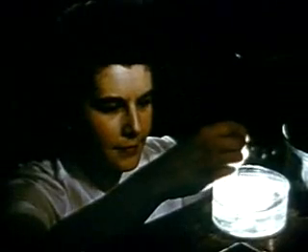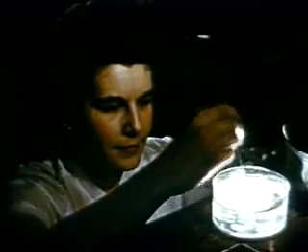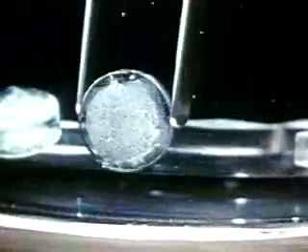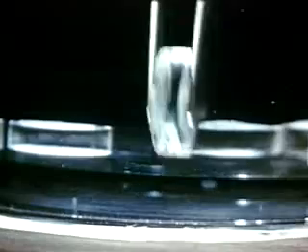okay. The liquid in the bowls is called xylol. It's something like benzene. It has most nearly the same index of refraction as glass, and because of this, tiny defects in the blanks show up better. This is just one of many 100% inspections that take place during the manufacturing process.